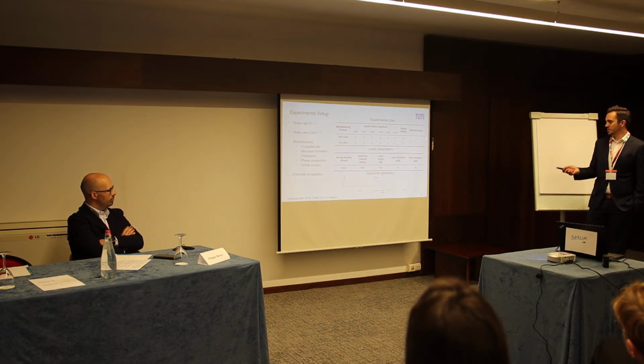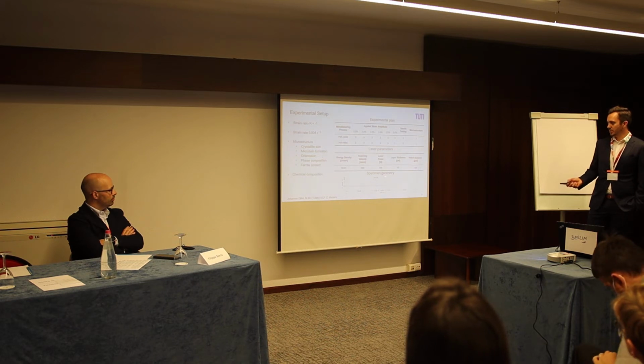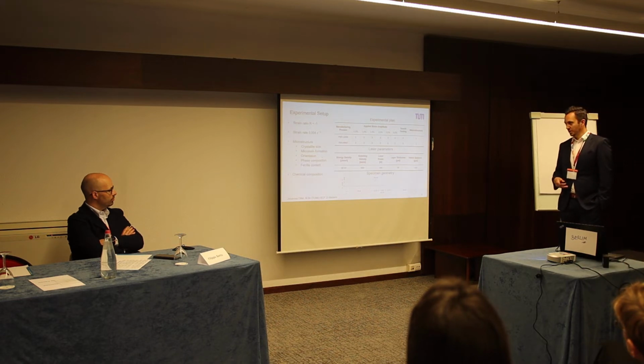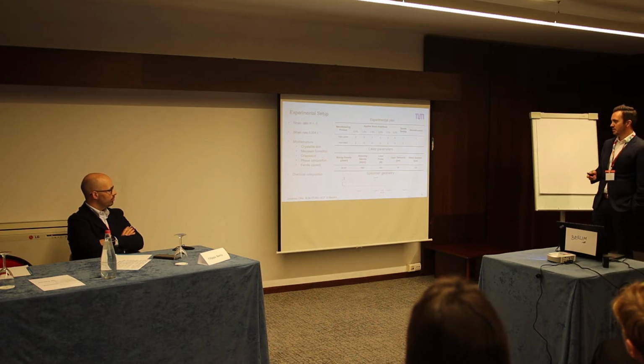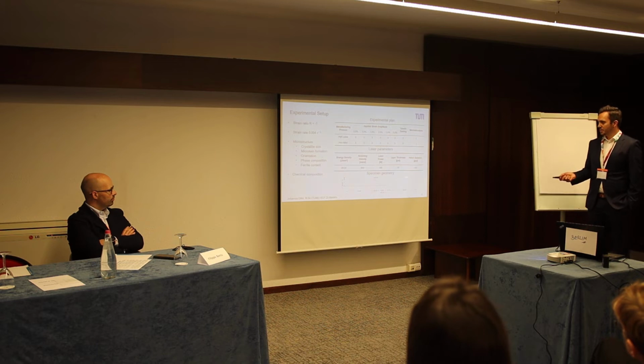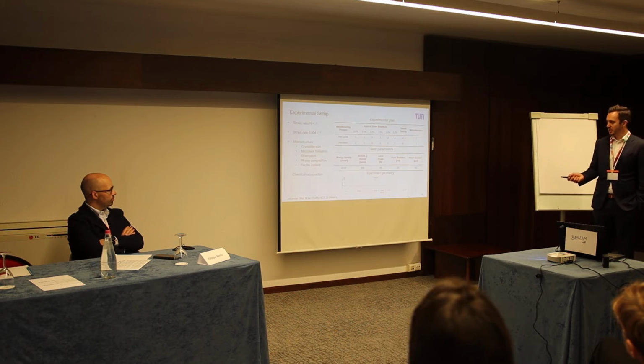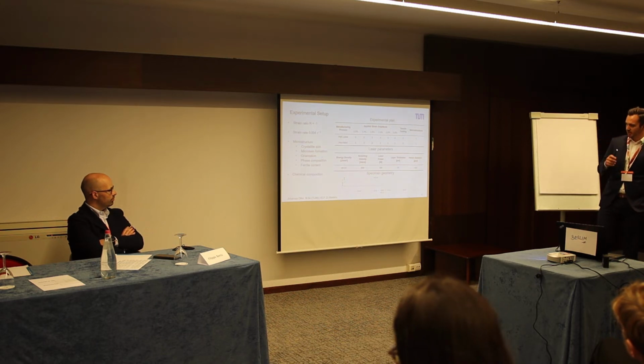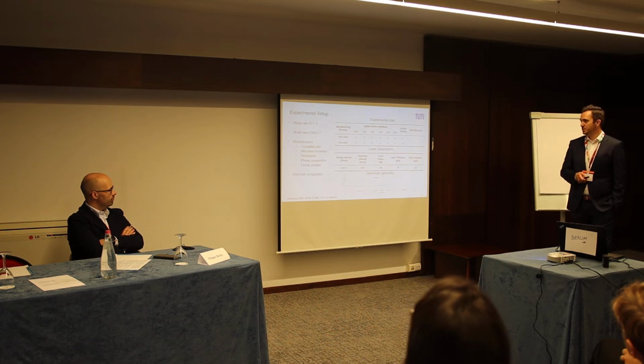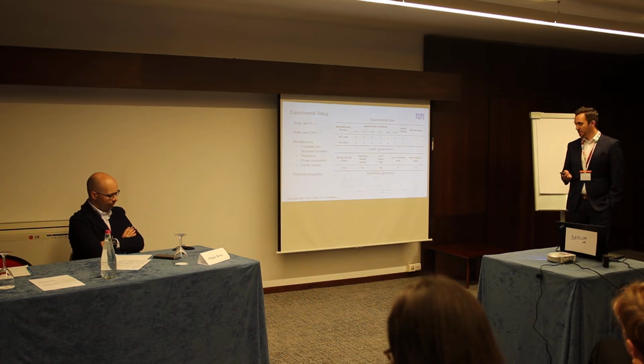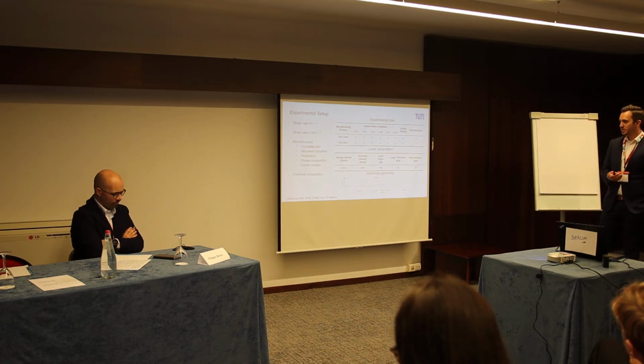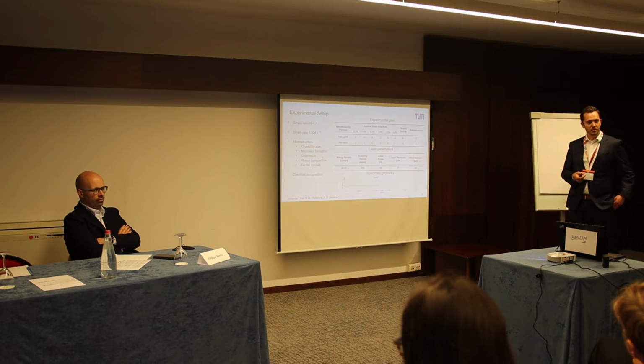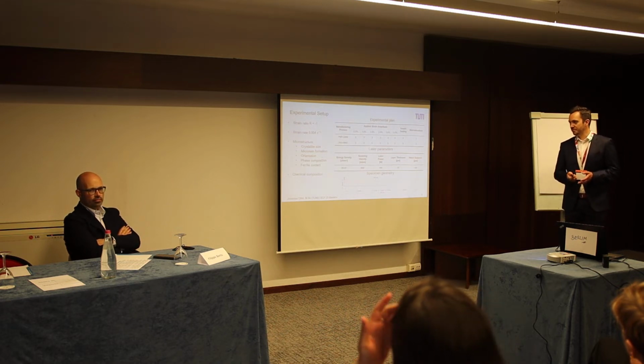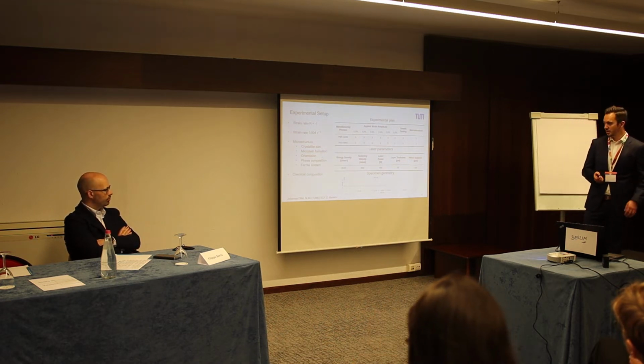We also used this specimen geometry, or at least this area in the middle here, to investigate the microstructure before loading. We also investigated it after loading, but I will get to this later. The applied laser parameters you can see here, resulting in an energy density of roughly 66 joule per cubic millimeter. And in the micro range, we investigated the crystallite size or cell size, the microtwin formation, the orientation, and the phase composition. And for the overall components, we investigated the ferrite content and the chemical composition.